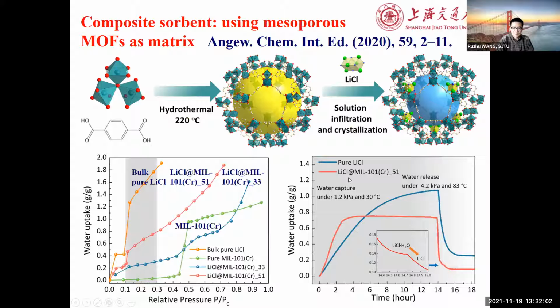And we also did research with MOF materials, combining lithium chloride with MOF materials. This line is for pure lithium chloride, and this one is for pure MOF material. Now we go in between, using a MOF material to sustain lithium chloride inside. In this case, what we found for the adsorption and desorption process is that it has a very enlarged performance.